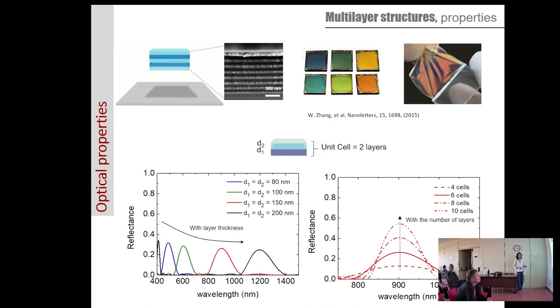Okay. So we know that in a multilayer structure, we are going to have this periodicity in the refractive index of alternating materials, and this is something nice to do because we can have nanometric control on the thickness of these materials. We can fabricate large areas also in a flexible or self-standing version, and we can deposit dielectric materials both in the dense or porous version. Okay. So by playing with the layer thickness in this one-dimensional photonic crystal, where we are going to have forbidden band gaps, photonic bandgaps, we can tune the position of this Bragg peak with the layer thickness, and we can also play with the intensity of the peak with the number of layers.